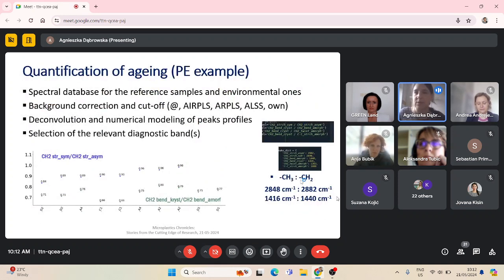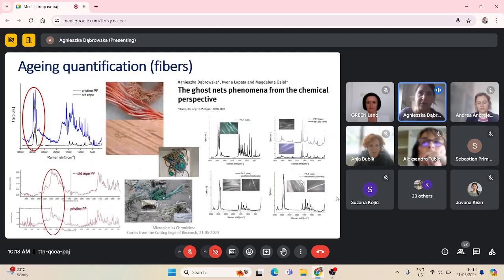The second thing is the so-called quantification of the spectra. So instead of only saying what type of microplastic and material we have, try to understand how aged it is. You probably know the carbonyl index, so the amount of oxygen groups we may determine as one of the features of aging of microplastic, but we also can have various other types of signal bands that we use for modeling. And this is what I am doing. So for different types of spectra, I'm trying to numerically propose the profile to do the deconvolution and to understand to what extent different types of bands are related to different chemistry on the surface.